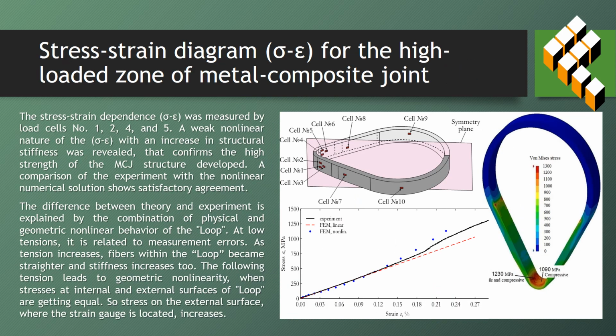The stress-strain dependence was measured by load cells number 1, 2, 4, and 5. A weak nonlinear nature of the stress-strain dependence with an increase in structural stiffness was revealed that confirms the high strength of the metal composite joint structure developed. A comparison of the experiment with the nonlinear numerical solution shows satisfactory agreement.